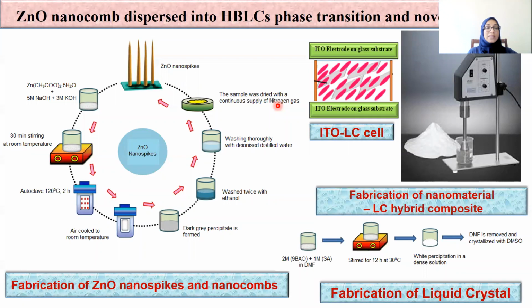Now let's have a look into the zinc oxide nanocomb dispersed into hydrogen bonded liquid crystal, phase transition and novel switching. This figure shows the various steps involved in the fabrication of zinc oxide nanocomb. Here, zinc acetate dihydrate is continuously stirred into alkaline media, that is 5 mol of sodium hydroxide and 3 mol of potassium hydroxide. It is continuously stirred for half an hour. A milk type solution was obtained.